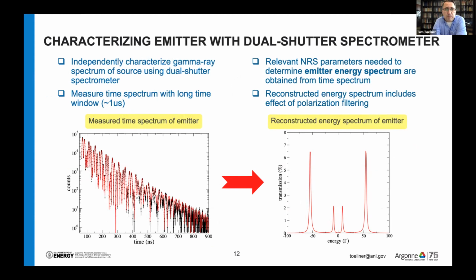From this measurement, I could determine all the nuclear hyperfine parameters so that I could reconstruct the energy spectrum of the emitter. And when I introduce the polarization filtering as well, I get the 6-line spectrum that we see here. One of the things I learned from this measurement is that there's a slight discrepancy after 400 nanoseconds. This is due to an incomplete magnetization of the film. And so the magnet that I had built for this purpose needs to be a stronger magnet in the future. And so that will be taken care of.